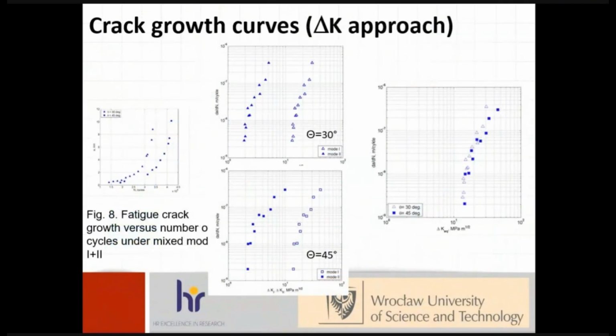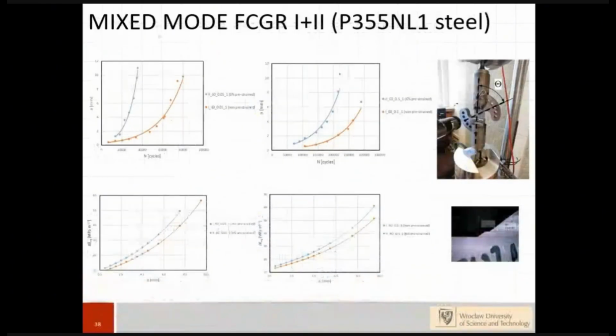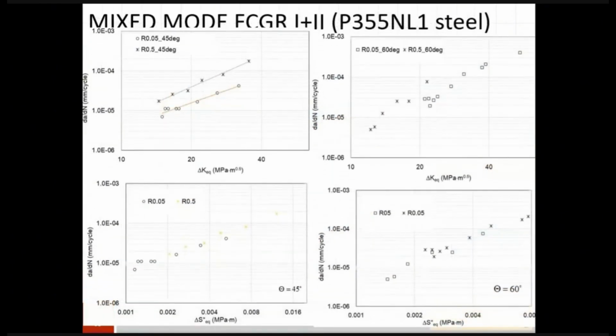For mixed mode, we also recently started to test under mixed mode. As we know, for mixed mode, we can also translate to an equivalent stress intensity factor, and the values are in the last slide of my presentation. We have the same effect for mixed mode. For P355NL1, still similar to S355 with the fine grain.